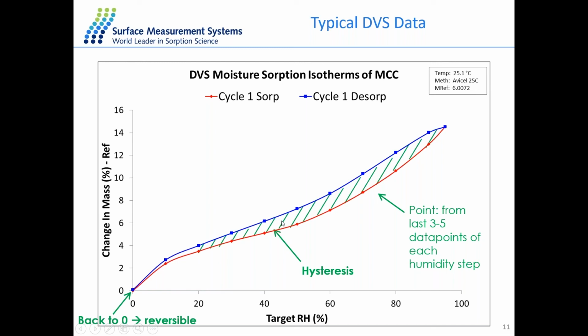So the gap here is called the hysteresis gap because of the water molecule traveling into the bulk of the material, and during the desorption process, it's a diffusion limited process that will give a different kind of kinetics compared to the sorption. But at the end of the desorption part, it's still going back to 0, so it's a completely reversible process.